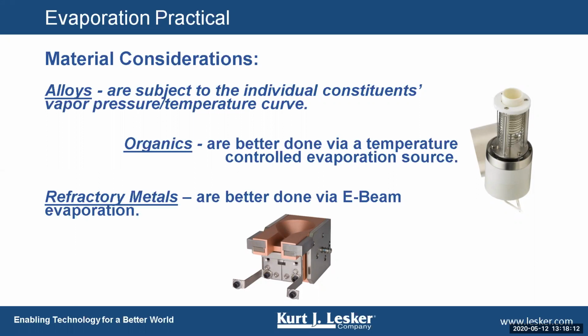For platinum evaporation, it tends to form a pit at the source after one deposition. Is there any sweep pattern that you can suggest so that it doesn't require such a high power? Or any other problem solving that you would suggest for platinum evaporation? Are you using a spacer underneath the crucible liner? If you use a spacer underneath the crucible liner, I think that'll even it out a bit because the material will get hotter and stay hotter for a given power level. Okay.